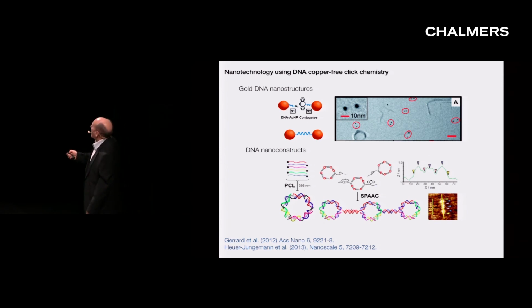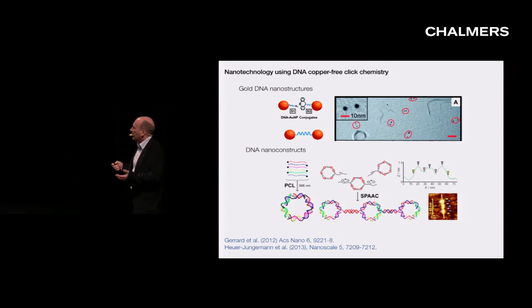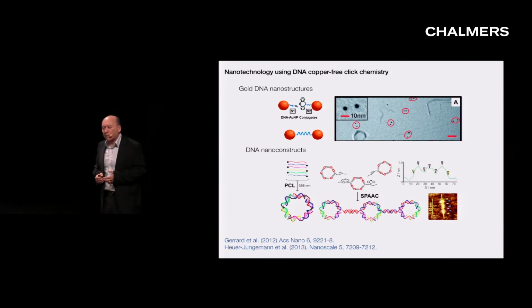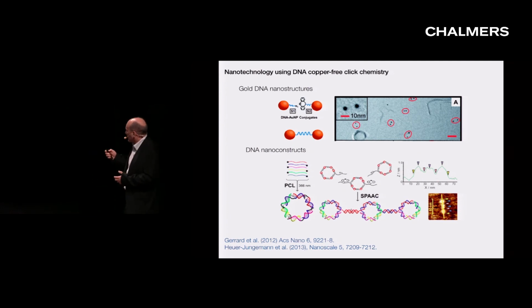So when we catalyze that reaction, we produce two gold nanoparticles held together with a single piece of DNA, which is permanently linked by a chemical bond. So we can carry out TEM studies, and we can observe the separation between the two gold nanoparticles, which is consistent with the length of the oligonucleotide between them. So it's a valency. This is, if you like, a monovalent gold nanoparticle.